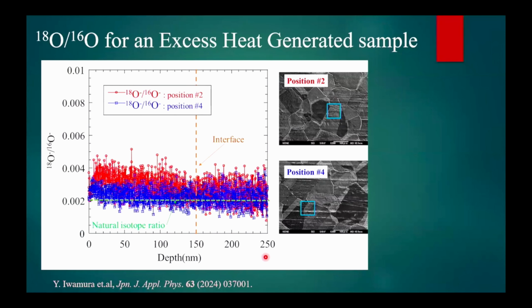And recently we analyzed this oxygen region. We can see the isotope ratio is different from the natural one. This data shows oxygen-18 over oxygen-16. Oxygen-16 is the major oxygen, and oxygen-18 is a little one. This line corresponds to the natural abundance, and at position 2 you can see large oxygen-18 over oxygen-16. So it is not the natural one, maybe the result of a nuclear reaction. So we are now analyzing the isotopic ratio in the very high oxygen region. Okay.